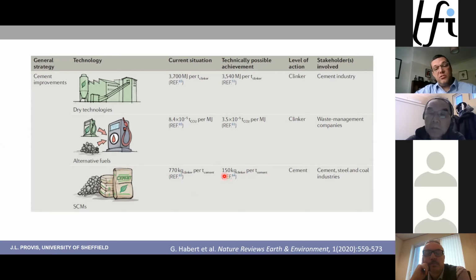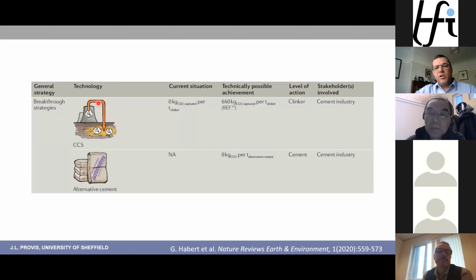We can change that to as low as 150 kilograms of clinker, so 15% Portland cement in a tonne of cementitious material. If we can find the slags, the ashes, the calcined clays, finely ground limestone, all these things that we'd like to blend to reduce the CO2 footprint, to reduce the clinker content of our cement and therefore our concrete. We can look at carbon capture and storage. And there's actually a roadmap, and it's a really interesting read in the UK cement and concrete sector, a roadmap to reach net zero, which leans very, very heavily on carbon capture and storage and requests funding from the government to please support us to achieve this.